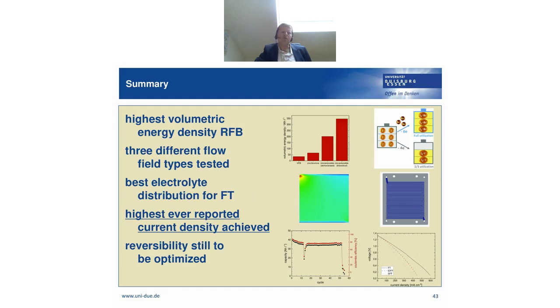So in summary, this zinc polyiodide redox battery is really interesting because of the high volumetric energy density. We tested here 3 different flow field types, and interestingly, the simplest flow field, the flow-through design, gave the best results. We obtained quite high current densities, which makes it in principle attractive. The goal, from my point of view, would be a flow battery that can operate with a current density of around 200 milliamps per square centimeter.